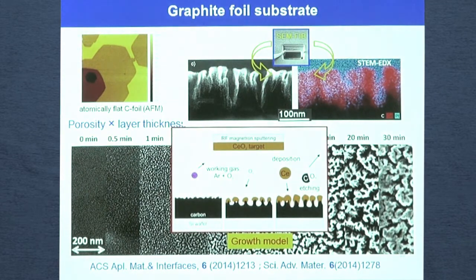The explanation is here. By depositing cerium oxide, we have oxygen which is removed from the target, but we can also add oxygen to the atmosphere, to the working gas, and create reactive plasma. And reactive plasma etches carbon very easily. That means that we are partially removing carbon from the substrate by forming CO2. But at the same time, we are depositing cerium oxide, which works as a nanomask, which means we are depositing nanoparticles which protect the carbon below these masking particles. Which means that we are at the same time forming the particles and etching the holes. And this is what can be seen in this figure.